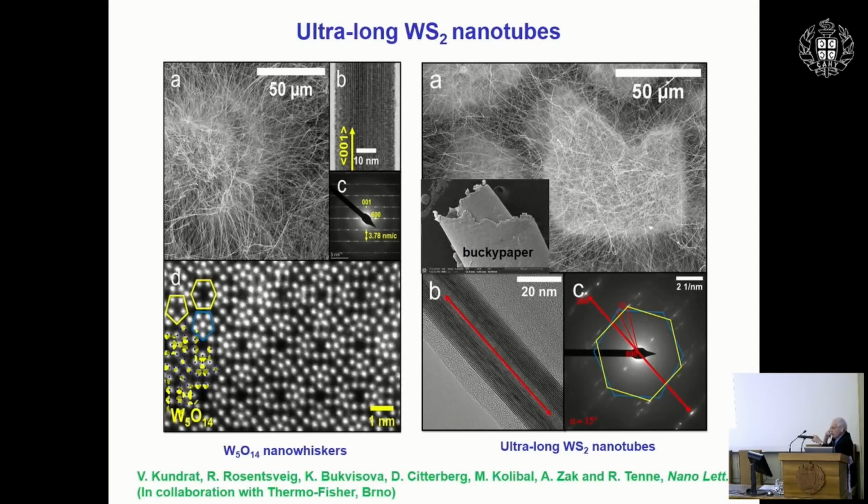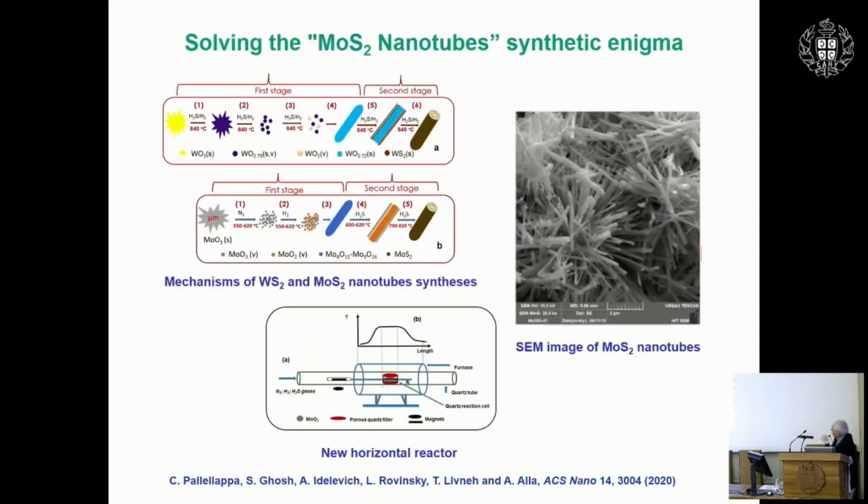So for carbon nanotubes, it's very easy to fold on itself and form single wall nanotubes, which is quasi impossible for molybdenum or tungsten disulfide or other inorganic layered compounds, because they are thicker and it takes much more energy, about 10 times more energy to fold them per atom. So here is the paper that describes this work.